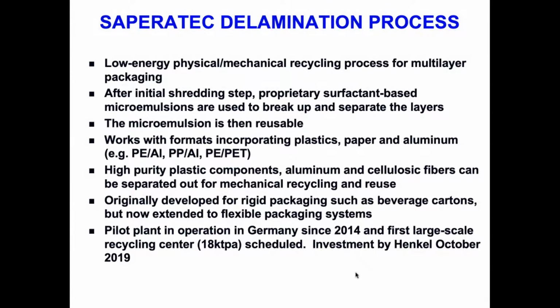First one I want to mention is the Saperatec delamination process in Germany. This is a low energy physical and mechanical recycling process for multi-layers. Here the packaging is shredded and surfactant-based microemulsions are used to break up and separate the layers. The microemulsion is reused, works with formats incorporating plastic layers and paper and aluminum, and you get back high purity plastic components and aluminum and cellulosic fibers, which can be reused. It was originally developed for rigid packaging, but extended to flexible packaging. There's been a pilot plant in Germany since 2014. They're looking to build a large-scale center, and Henkel made a big investment in this company back in 2019.